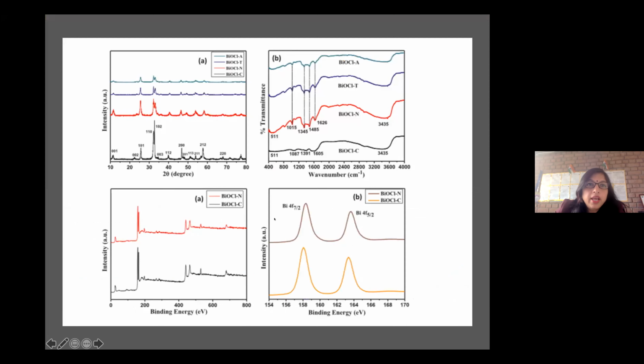So then this is again the XRD, and this is FTIR, which shows the neem leaf extract: keto group, hydroxyl group, and other groups are present according to the leaf extract, which has organic groups. So it showed, and then by XPS, it was proven that these are bismuth.